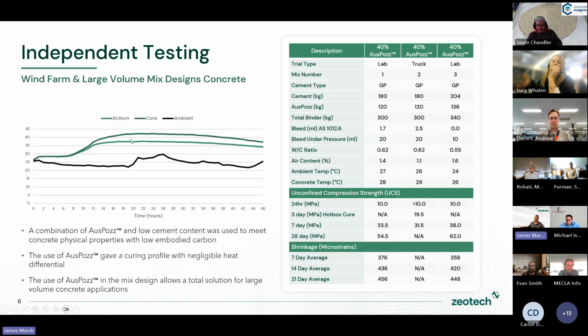So what we saw here was, look at the bottom versus the core. Well, the temperature differential actually stayed quite small. We're talking about a maximum here of about 47, 48 degrees at the core, and the bottom about 36, 37 degrees. So a very small temperature differential. That was still higher than we wanted. So the work we're doing now is going to be a 50% AusPozz. We think that should give us a temperature differential of around about 4 degrees only between the core and the bottom, as well as meeting the other requirements. So that's the technical work.